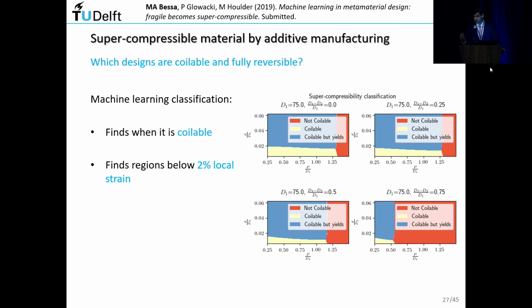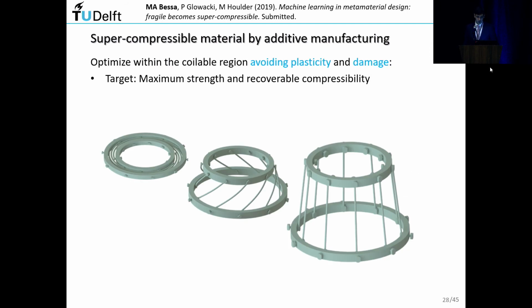And then you just need to take the database and classify into three regions. The red region that you see there is what was the white before. So the red region here is not coilable, not interesting designs. The blue region is coilable, but the local strain is above 2%, so it would plastify or break. And the yellow region here is coilable and reversible. So this is saying, again, without doing experiments, that it's actually possible to have these materials, coilable and reversible, to obtain this behavior. So we did that.